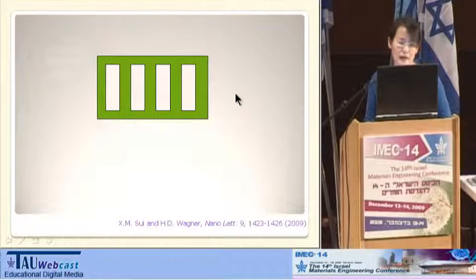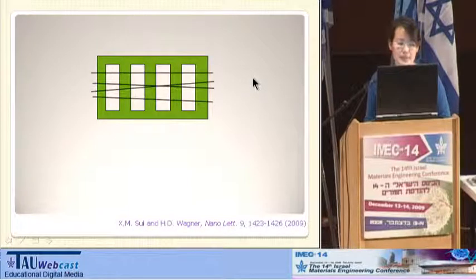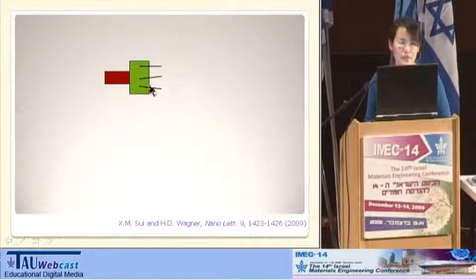This is the principle of our process. First of all, we have this aluminum collector. We cut it into several trenches, which allow us to align the electrospun fibers onto it. And then we cut the aluminum collector along this dashed line, and take this part, put it onto the holder of the nanomanipulator, and then